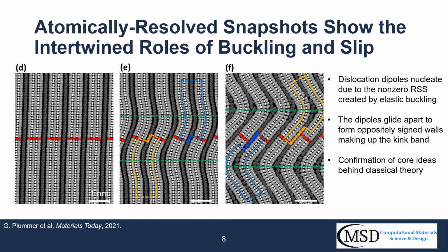These are indicated by the Burgers circuits in yellow and blue, depicting oppositely signed dislocations. Additionally, the red-colored atoms show a column of atoms initially with zero disregistry, which then develop increasing disregistry as the dislocation dipoles nucleate. This process repeats itself inside the kink band, nucleating additional dislocation dipoles and thus increasing the kinking angle and relieving more in-plane strain. The results we see here are the first dynamic demonstration of this mechanism and largely confirm the core ideas of classical kinking theory from 70-plus years ago.